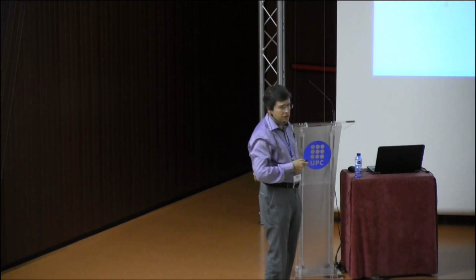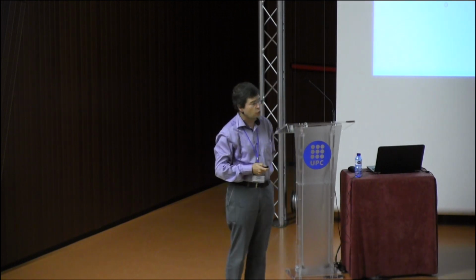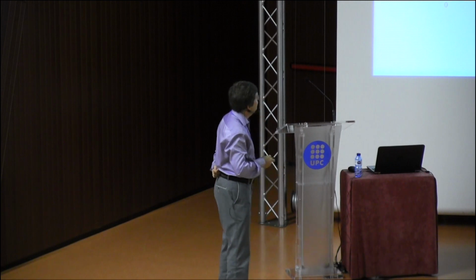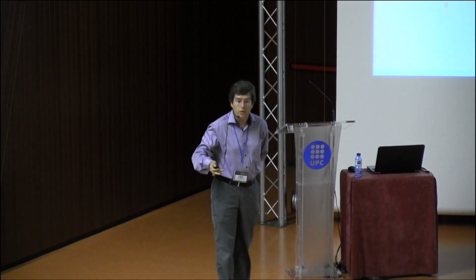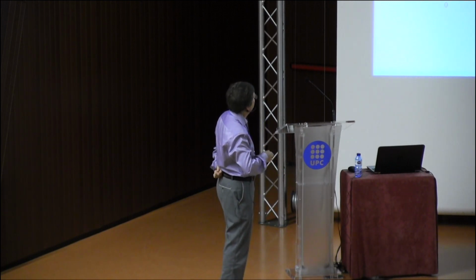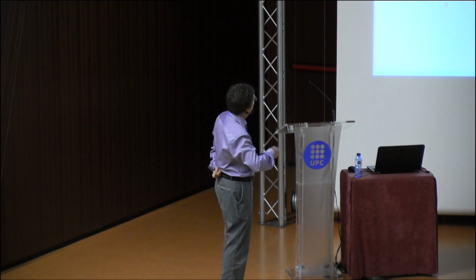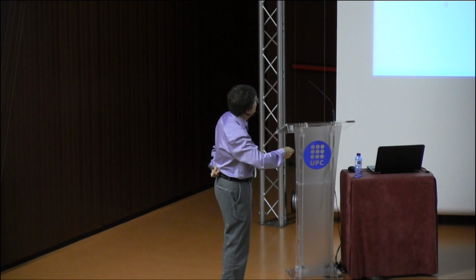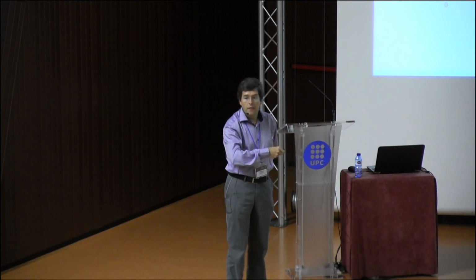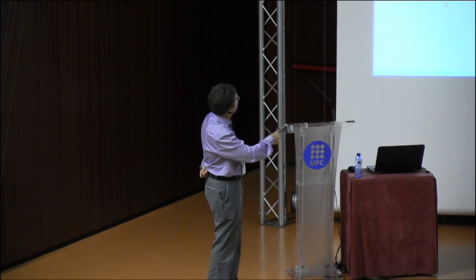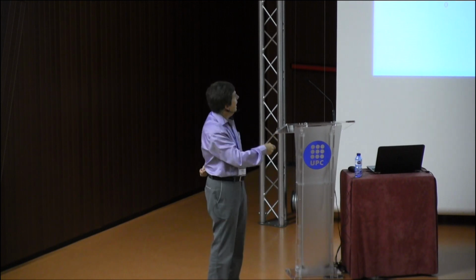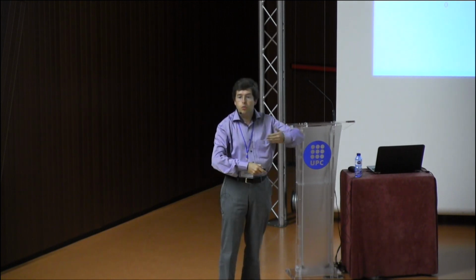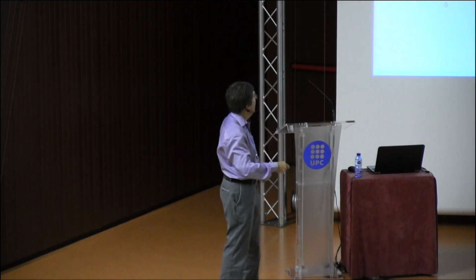If you try to simulate this, as is done a lot in industry, especially in steel industry, what you do is take a constitutive law - this dotted line - where you have softening and then hardening. The softening will induce localization, and the hardening will induce propagation of the band.